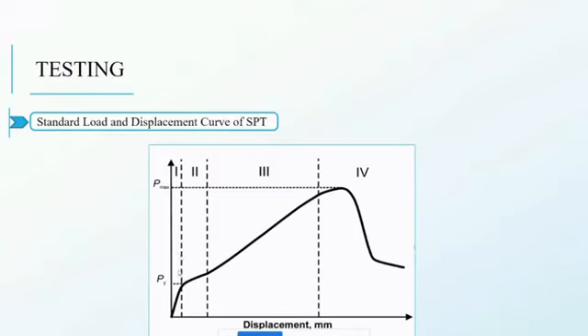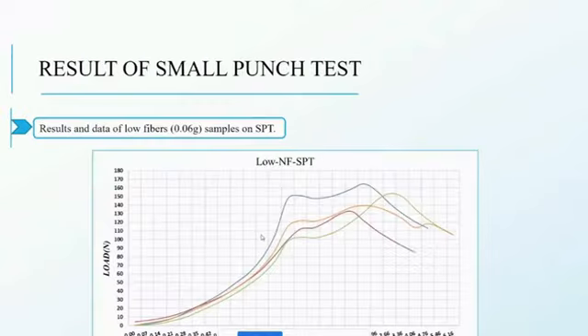This is the transition between elastic and plastic. We go to the stretching here until we get the fracture. So we try to see how the sample behaves during the small punch test, even when we add some fiber. I'm not going to say it increases ductility, but it makes the material stiffer.